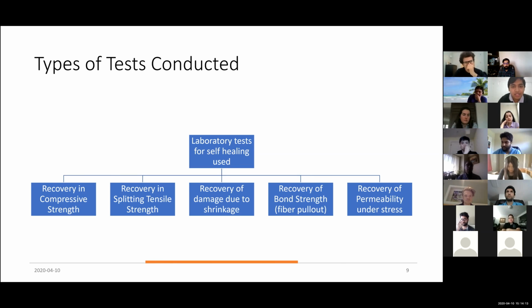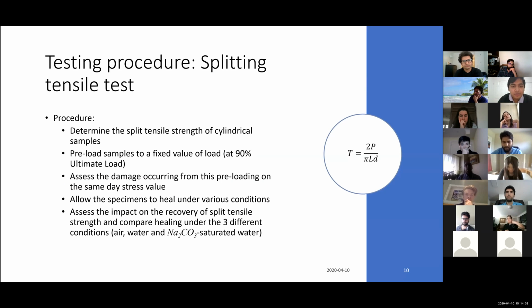In my analysis, I have conducted the following laboratory tests for quantification of healing: recovery in compressive strength, in split tensile strength, recovery of damage due to shrinkage, recovery of bond strength using fiber pullout, and recovery of permeability of concrete when a stress is applied. For the split tensile strength test, first I tested 5 cylinders up to their ultimate strength, to know the ultimate load at which it fails. Then I tried different percentages of loading, and I found 90% of the ultimate load is able to induce some damage for split tensile measurements.